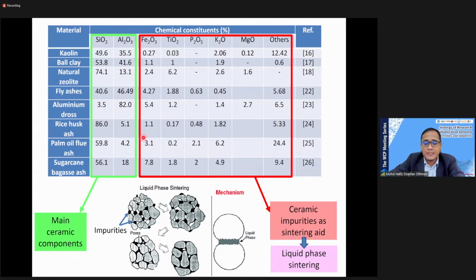So when you sinter the membrane at 1,200, these types of impurities will melt and will act as a glue to bind the grain between the silica and alumina, and therefore we can further reduce the sintering temperature. So this is one of the good advantages of using this alternative material.